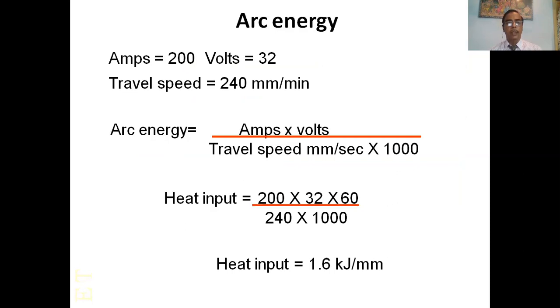Arc energy: say amperage is 200, voltage is 32, travel speed is 240 millimeter per minute. The arc energy is equal to amperage times voltage divided by travel speed in millimeter per second, divided by 1000. So heat input is 200 times 32 times 60 divided by 240 times 1000. So heat input is equal to 1.6 kilojoule per millimeter.